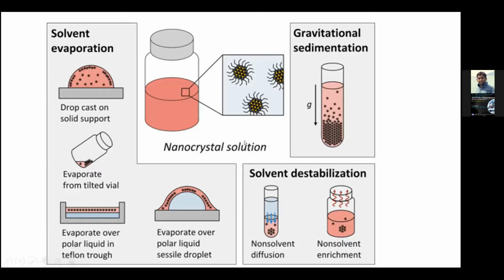Otherwise, because in air there's lots of moisture, due to the saturation of the moisture, the solvent can go fast. Like if you took toluene or hexane, it can go fast. So you need to add something like octane or decane, so it can be removed slowly, and the nanocrystals slowly aggregate, and when it's aggregated on the film, it's organized on the surface.